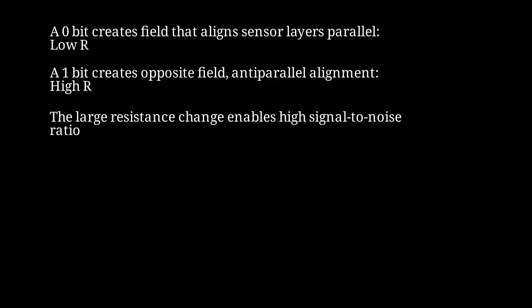When a 1 bit passes, its opposite field creates antiparallel alignment, giving high resistance and a high voltage signal. The large resistance change, 50% or more, provides an excellent signal-to-noise ratio. This enabled bit densities to increase by more than a factor of 100 since GMR was introduced in 1997.